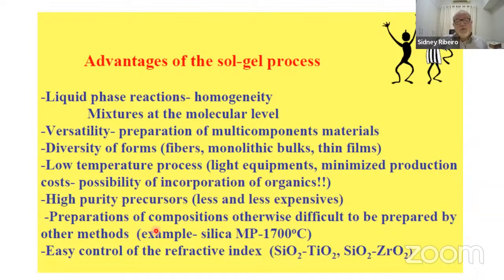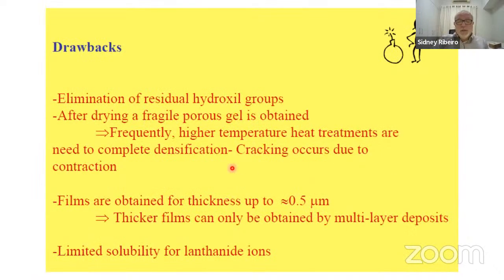So you can prepare, for example, compositions that otherwise would be difficult to prepare. For example, silica titania, silica zirconia, the melting point of these mixtures is very high, and you can prepare them at almost room temperature. So there are some drawbacks, of course. You will always have hydroxyl groups. After drying, a very fragile porous gel is obtained. Frequently, higher temperature heat treatments are needed to complete densification. And in this case, cracks will occur due to the contraction. Films are obtained for thickness up to 0.5 micron, not more than that. So thicker films can only be obtained by multilayer deposits. And of course, there's a limited solubility for lanthanide ions.